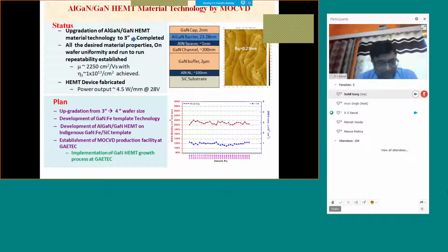and the plan is to upgrade now the wafer growth to 4-inch. And presently we are using buffer resistivity layers with carbon doping or by introducing dislocations, but the best results obtained or reported are with the iron doped buffer. So we are now in the process of installing one new MOCVD with this iron doping capability. The system has already arrived in SSPL and is under installation, and we hope to get by the end of this year our own HEMT structures with the iron doped buffer.